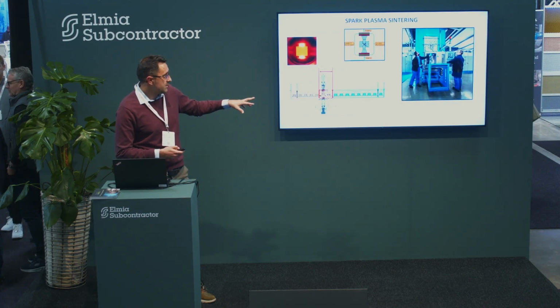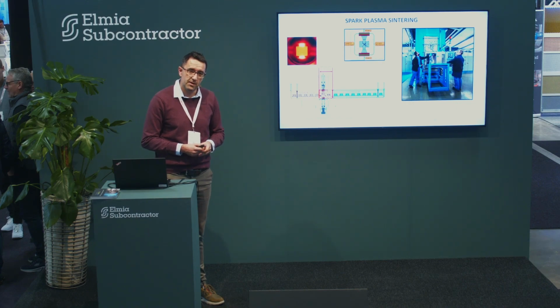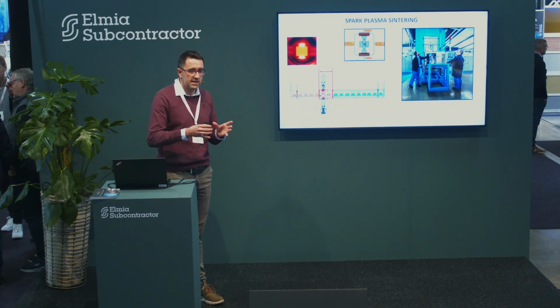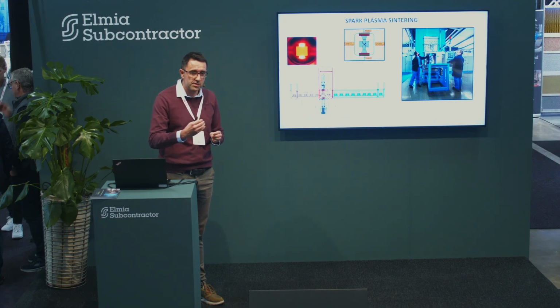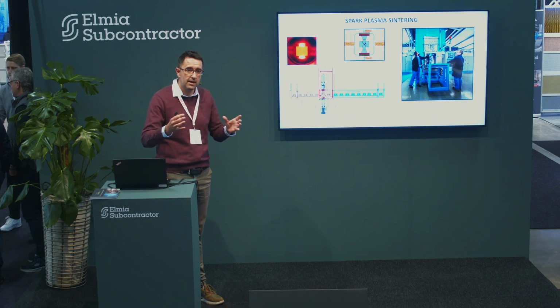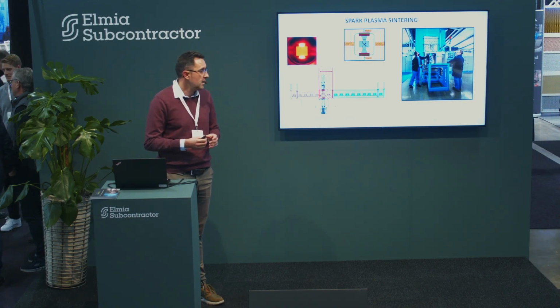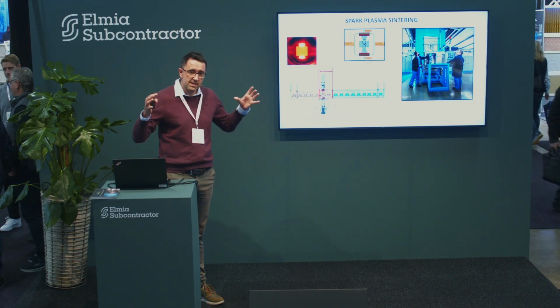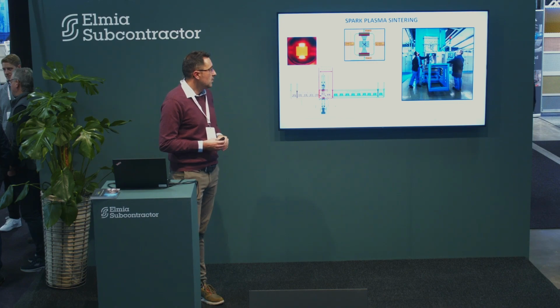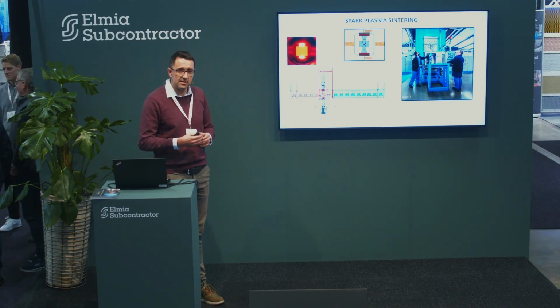Before going on to the next materials, I would like to explain a little bit about one of the technologies that we have at Nanoker for producing ceramics. As you know, ceramics need a heating process, a sintering process, to get full densification of the material. It's normally done in batch furnaces with resistance heating that heats the material indirectly. In this case, in spark plasma sintering, what we have is a pressure-assisted sintering technology.